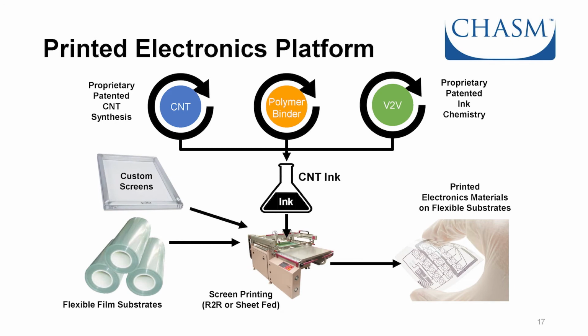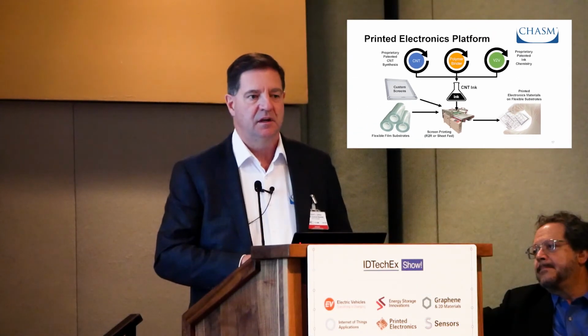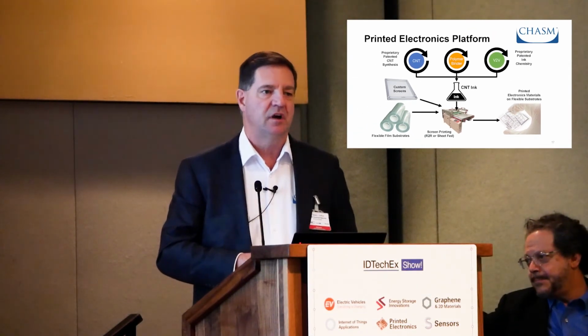Another thing is we have technology that allows us to disperse carbon nanotube organic paste into this ink vehicle without the use of surfactants. So when we print this ink onto a substrate, we're not leaving behind surfactants, which are viewed as a contaminant for the printed electronics. We use polymer binders, and this is an area of active research for us. Currently, we're using an acrylic polymer binder, which is really nice for thermoforming. We also, during 2020, expect to bring to market a UV curable polymer binder, which will have even better encapsulation properties and very good scratch resistance. We're also developing an elastomeric polymer binder for stretchable wearables applications.